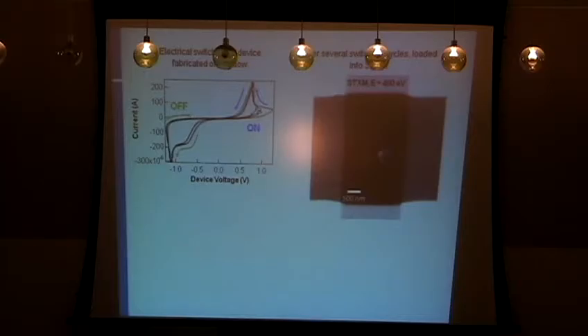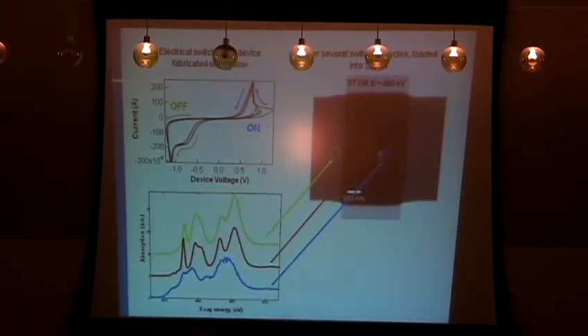Okay, so here's some actual data. So these devices were fabricated the way I just described, and here's the electrical data that I saw: very nice bipolar resistance switching, very similar to the types of data that we've been publishing on devices that are not on windows. So what I did was I cycled this device a number of times, less than ten, and then went ahead and loaded it into the system. So what you're seeing here is actually an X-ray image of the device at an energy of 460 eV. You can see the top electrode, bottom electrode right here, and here's the junction area. And already inside this junction, you actually see some contrast within it. Now every single pixel that you have here, in fact, you have an entire spectrum associated with it.